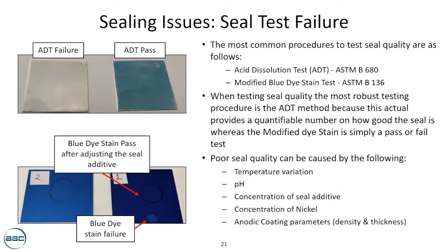Now, the seal test failures. As mentioned before, the most common tests used in the industry are the acid dissolution test and the modified blue stain test. If you see the picture at the top, you can see two parts: a part that failed the acid dissolution test and a part that passed the acid dissolution test.